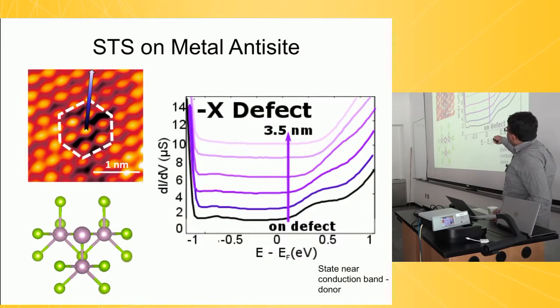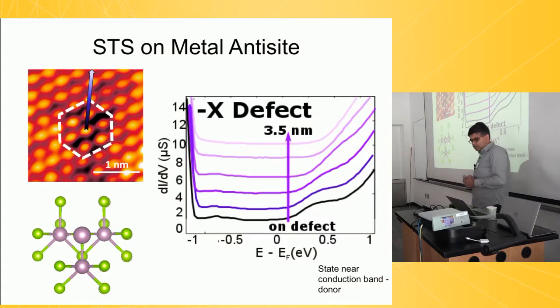If we go to the metal anti-site and measure carefully what the spectrum looks like, we see this nice little additional state that exists on the edge of the conduction band. A state on the edge of the conduction band is a donor state, if you remember your semiconductor physics. We can characterize how far away from this defect this state exists. It exists about 3 nanometers away, and if you go 3.5 nanometers away, the impact of the state is gone.